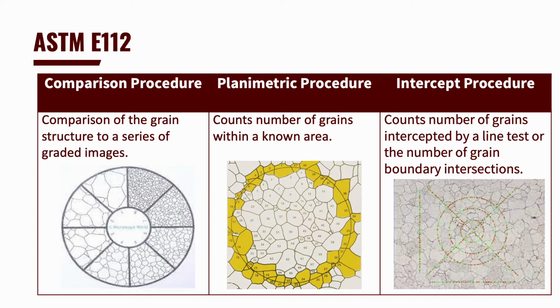The planimetric procedure involves an actual count of the number of grains within a known area. The grains must be inscribed in a circle. The need to mark off all the grains to obtain an accurate count is a downfall to this method because it is more time-consuming than the intercept method.